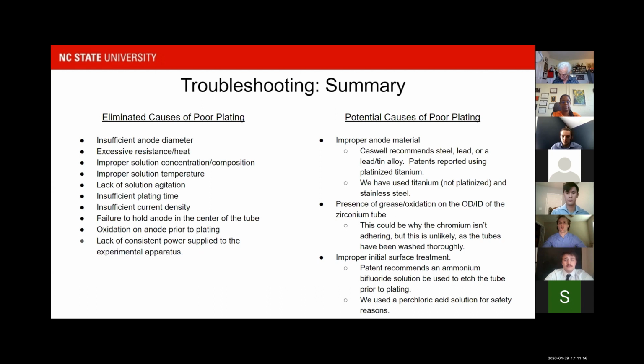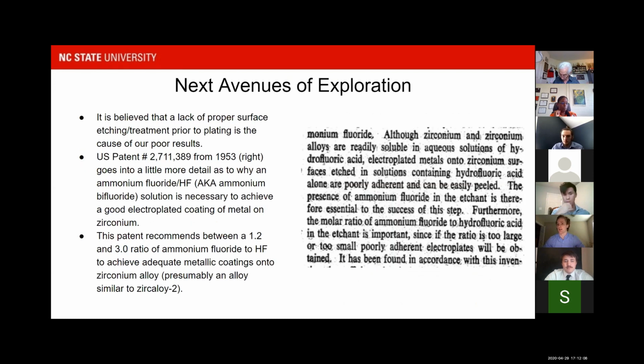But the biggest culprit that we all agreed on for why we were not seeing a chromium plating on the inside was an improper surface treatment. The patents that we were able to find in the experimental literature recommended using ammonium bifluoride, and due to safety concerns, we stuck with perchloric acid. So I'll leave it up to Liam to go from here.